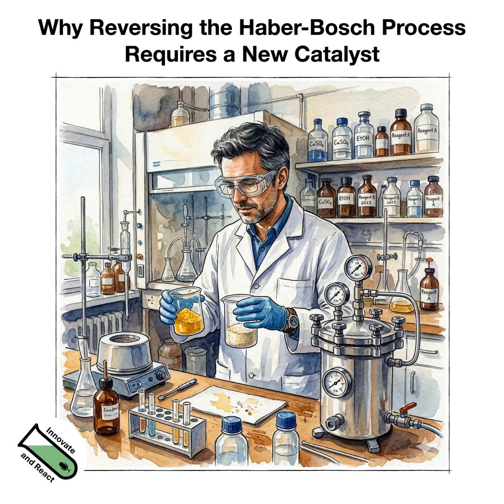And you can look at that with the already mentioned concept of microscopic reversibility, because that is of course the very prominent challenge in ammonia synthesis. You want to split it. But in fact, the energy barrier on the way back or forth is not so different. So it's also a problem if you go the other way around, because you also need to go over a similar transition state. And that makes it also a challenge in ammonia decomposition to form those nitrogen molecules.